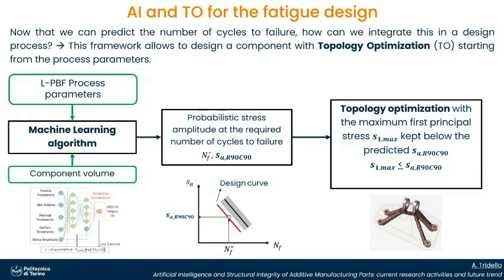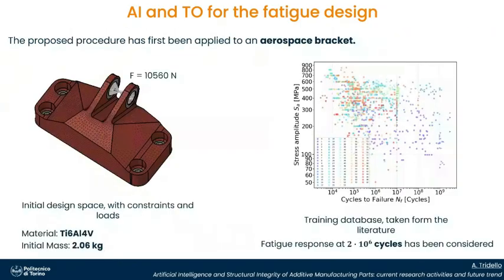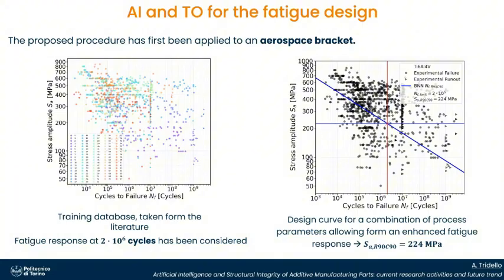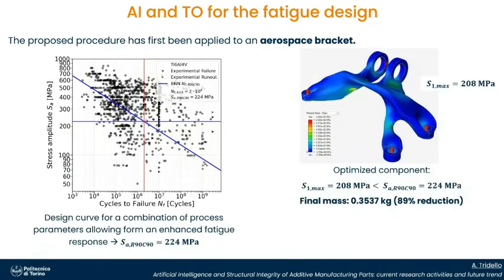So we have a process which takes into account during the topology optimization the effect of the process parameter and their influence, and this is not done in the literature and the industrial practice. In general, only static properties are considered. So we have validated this one with this CAD bracket that you find in the literature with this material, titanium. This is the training data set taken from the literature for the titanium alloy. Here you can see where we have selected the number of cycles to failure, okay? And here are the results.